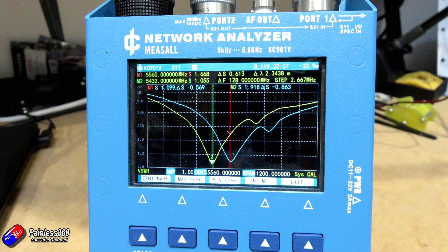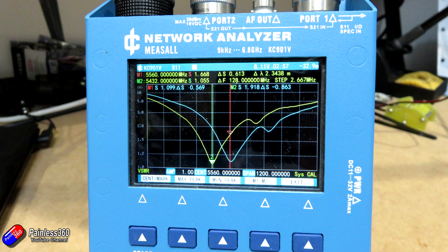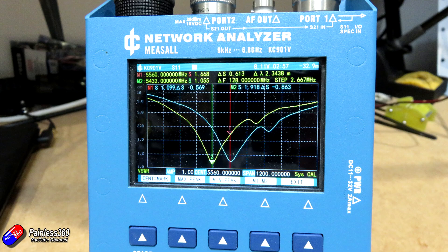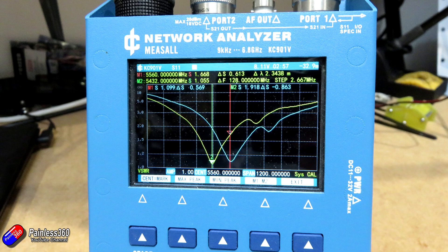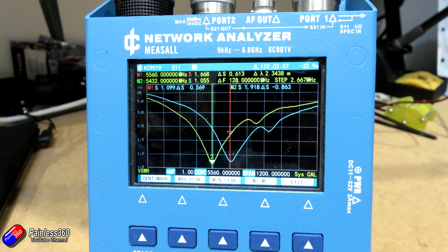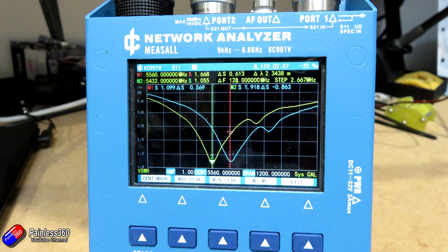Again, if your antenna was working fine around 5560—that red line—and it was okay before the shroud, if you put a PLA shroud on, the VSWR is going to jump from about 1.1 up to about 1.6 to 1.7, which will affect performance and the amount of radiated energy.